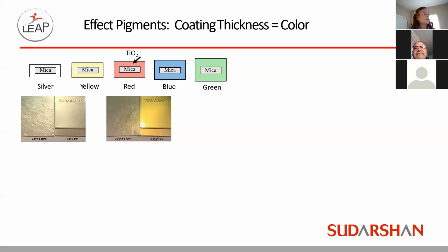On the left, we did this with a two-roll mill to prepare these swatches, which allows the wavy, veiny types of effect to show through from that mica. So you see some of those bright spots and shadow spots along with each of these.